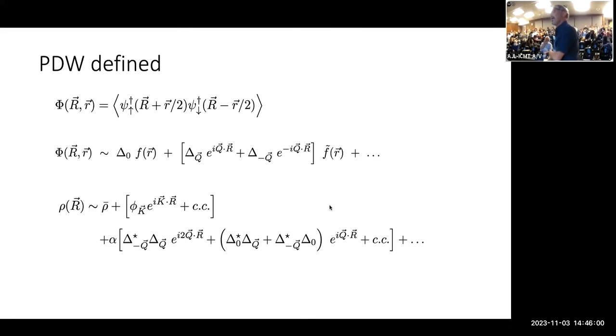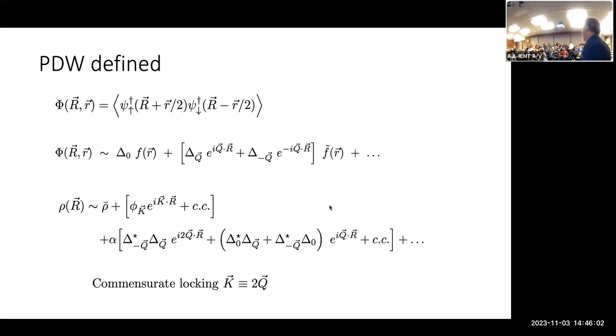In the problems that I'm going to be looking at, there is a commensurate lock-in between the putative pair density wave and the very clear charge density wave. And you can imagine that if you have this wanting to make charge density oscillations at 2q and some other physics making you want to have oscillations at k, if they're anywhere near each other, there are going to be terms in the Landau theory that lock them together and cause them to be mutually commensurate with each other.